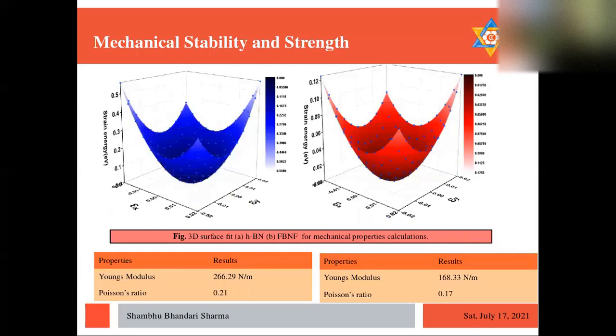And further, we found the elastic constant like c11 and c12 and c66 and we check the Born stability criteria and we found that both monolayers are mechanically stable.